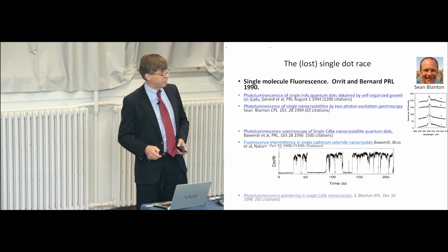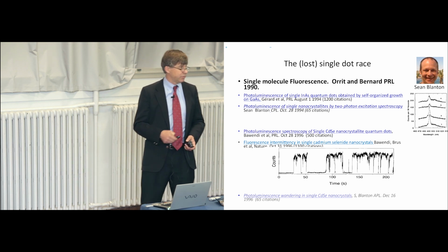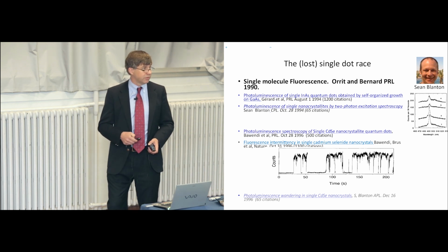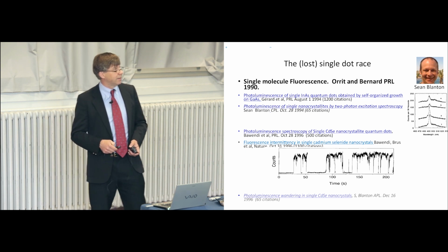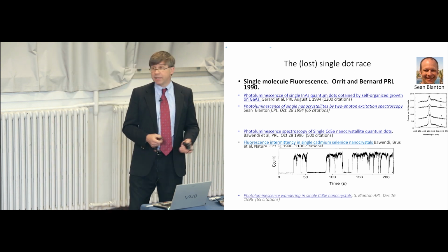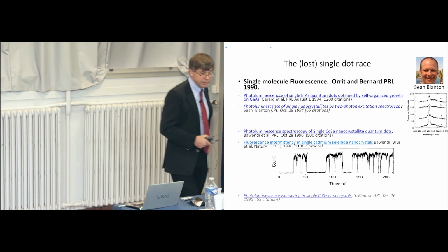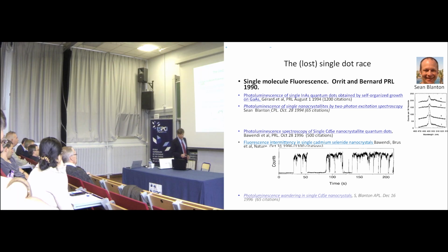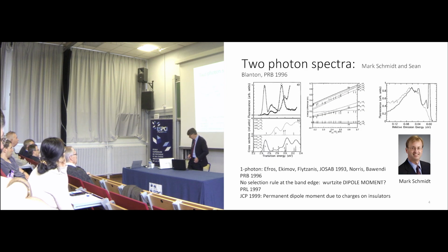We continued this work for a little bit more. In fact, this paper was rejected by PRL, so it took about 8 months to get it published. So we lost again on this time scale. But again, our data were not as good. Two-photon spectroscopy of single particle was just not as nice as one photon. So that was a lost race. We still learned some things.